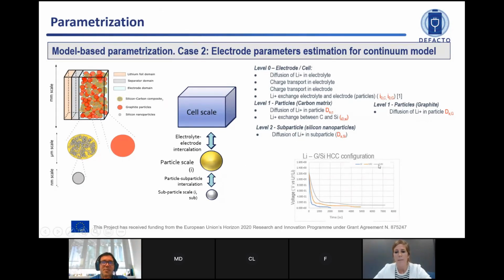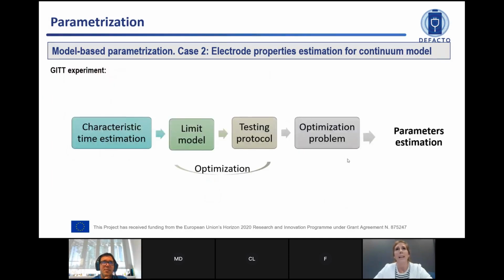So these are the results at different C rates, but considering the parameters from literature. Something we've been working on is how to obtain these parameters for our specific case. Again, we rely on the electrochemical tests, and on the GITT experiments that we have used in the past to obtain the OCV and the solid diffusion coefficients. Here, instead of applying an analytical equation, we want to include the full model, but it is quite computationally expensive, and we need to somehow reduce or simplify the model.